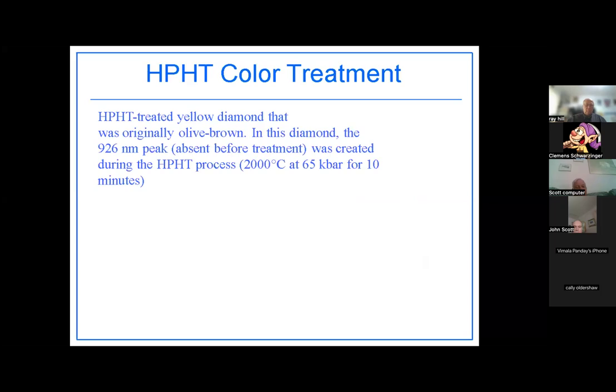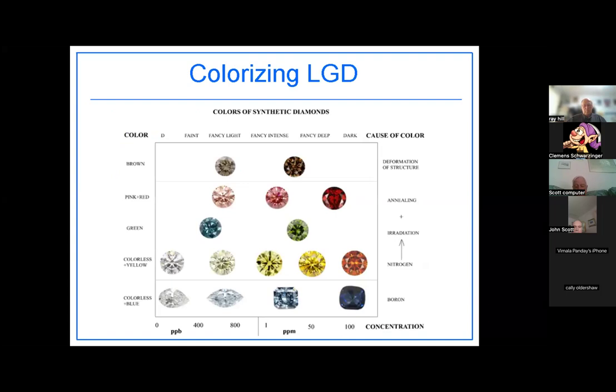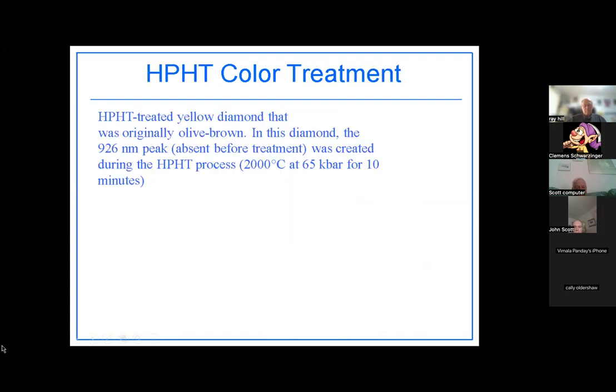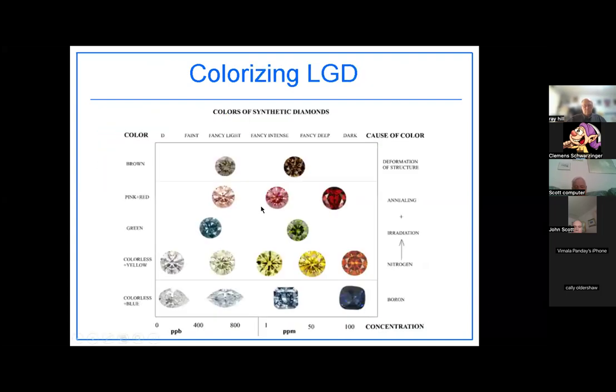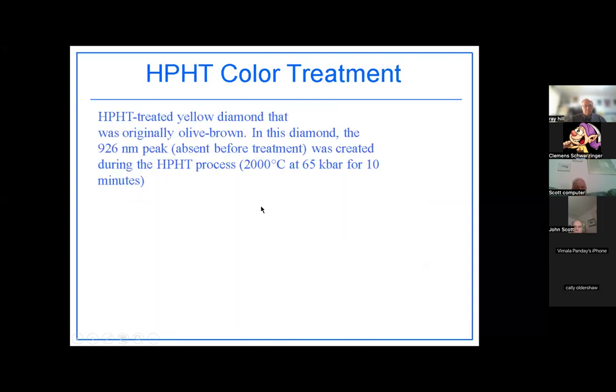All right, so here's a yellow diamond that they treated. It was originally olive brown, and the 926 nanometer peak was absent before treatment, created during the HPHT process. They heated it up to 2000 degrees centigrade at 65 kilobars of pressure for 10 minutes. And I'm not sure what happened to my picture. Well, you'll just have to take my word for it. I think this is actually the one that I showed you a few slides ago.